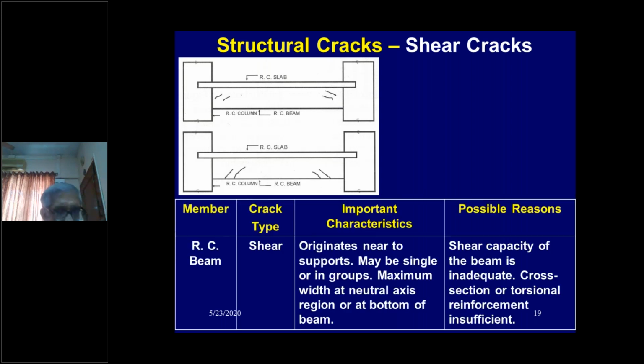Shear cracks. It is very easy to identify shear cracks. They occur at a 45-degree angle. They don't occur vertically or in any other direction. They originate near the support and may be single or in groups. Maximum width at neutral axis region or at the bottom. This is the neutral axis region when there are fixed end supports. And here you can see it at the bottom. So shear capacity of the beam is inadequate, cross section or torsional reinforcement insufficient.